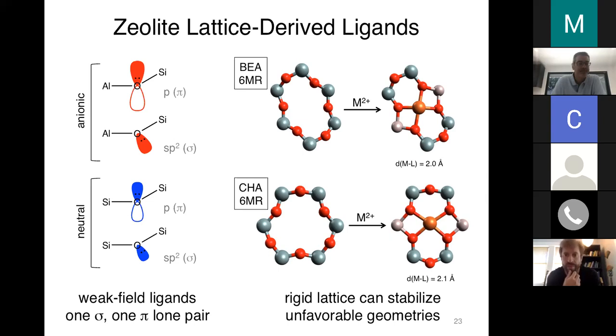So for example, if we look at this 6-membered ring that's in the beta type zeolite, this ring doesn't really have to distort much to accommodate a square planar metal ion. However, the Chabazite 6-membered ring, which has trigonal symmetry, needs to distort considerably to accommodate a square planar ion. And as a result, the metal ligand bonds in this lower structure are significantly strained. You can see that in their predicted metal ligand distance, which is elongated by about 0.1 angstroms. So in this case, strain from a zeolite lattice can play a pretty big role in determining how these oxygen atoms donate into a metal ion.